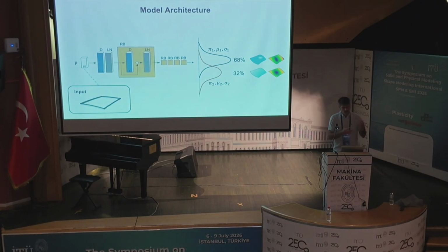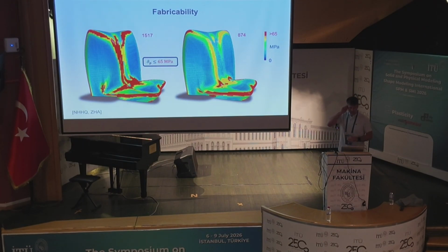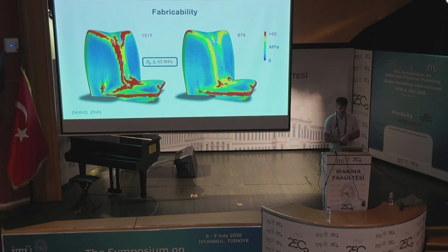Second, being able to predict not just one, but multiple stable states is a big advantage compared to a pure simulation-based approach, where it would be fairly easy to identify one local minimum of the deformation energy, but it's hard to reliably find both. So the advantage goes beyond just being faster. Now, this is also differentiable, so because of this, it supports quite straightforward shape optimization. And here is just one result I want to show you briefly.